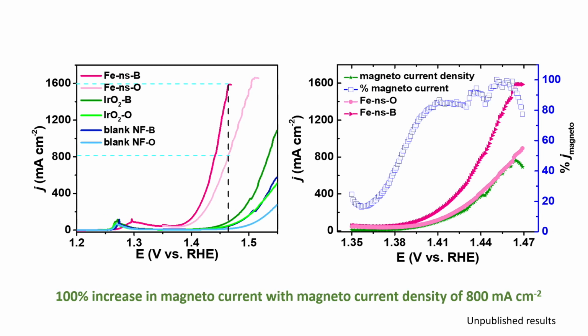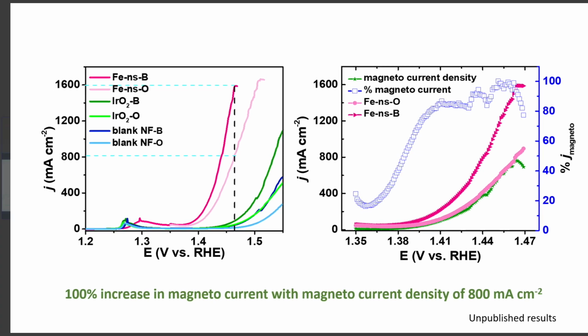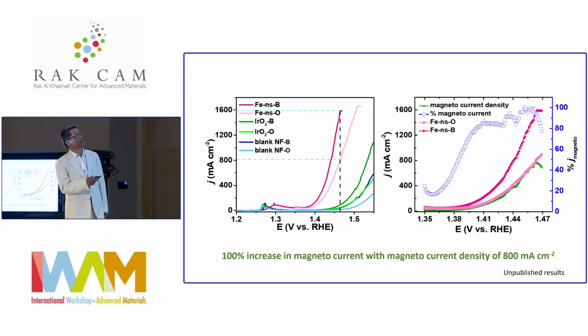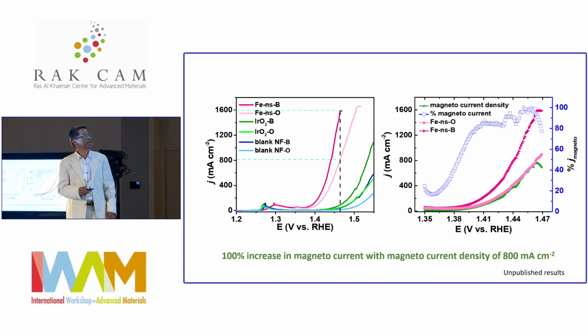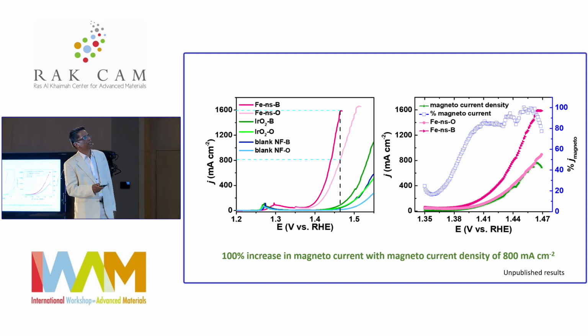If you look at the iron nanostructure, O means in the absence of magnetic field, B is in the presence of magnetic field. We applied a magnetic field of around 150 millitesla, just a normal magnet, and you can see that at around 1.46 volt there is a huge jump with the magnetic field, whereas for just nickel foam, where we put this catalyst on nickel foam as the current collector, and for iridium oxide, you won't see any big difference.